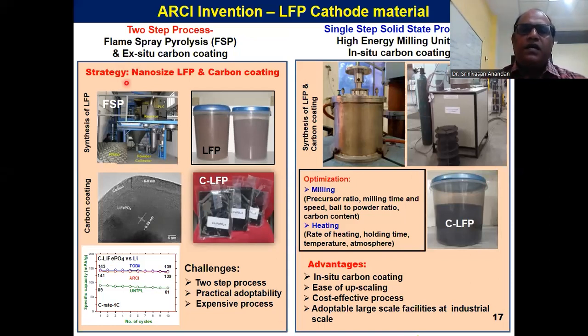The strategy which we have adopted is to prepare nano-size LiFePO4 to increase the lithium-ion diffusion kinetics during the charging discharging process, and to have a uniform carbon coating to improve electron transport during the charge discharge process. Initially, we used a two-step process. First, we synthesized nano-size LiFePO4 cathode material using our pilot plant facility called flame spray pyrolysis. We dissolve lithium, iron, and phosphorus salts in an alcohol solution. Finally, we introduce it into a high temperature flame where it undergoes pyrolysis. Subsequently, the melting, nucleation, everything takes place. Finally, we get nano-size LiFePO4 particles.